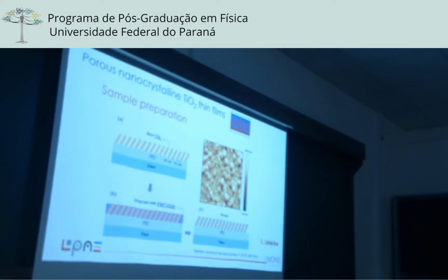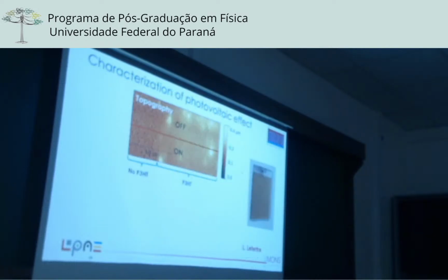So we have the bare TiO2 on ITO, we drop cast the P3HT, and then we rinse. In fact, what we have is TiO2 covered with the P3HT. This is what we have for TiO2. Here we have the topography, with no P3HT, we just put it in the solution. So we have P3HT on the right, no P3HT on the left. On the top, no light. On the bottom, light. What happens for the photocurrent? Where do we expect to see some current?